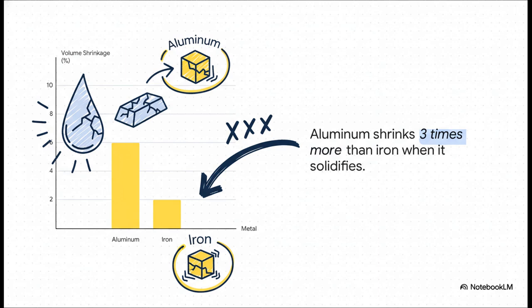This chart really gets to the heart of it. Just look at that difference in shrinkage. As it goes from a liquid to a solid, aluminum shrinks by about 6%, which is 3 times more than iron does. All of that shrinking creates a ton of internal stress inside your brand new weld.